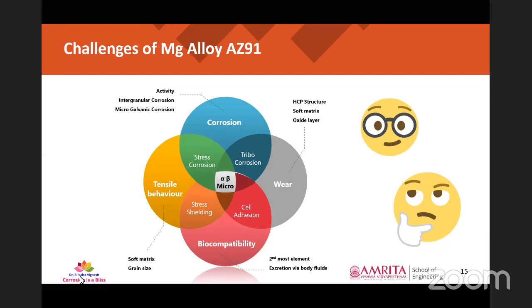When we combine tensile behavior and corrosion, we get stress corrosion cracking. Corrosion and wear give tribo corrosion. Tensile behavior and biocompatibility come with the stress shielding effect. All these characteristics depend on the microstructure of the alloy, which consists of alpha phase and beta phase. Alpha phase is the primary phase of AZ91, that is alpha magnesium, and the beta phase is an intermetallic of magnesium and aluminum in the alloy itself. So if we can engineer the micro constituents of this alloy, we can get a good result.